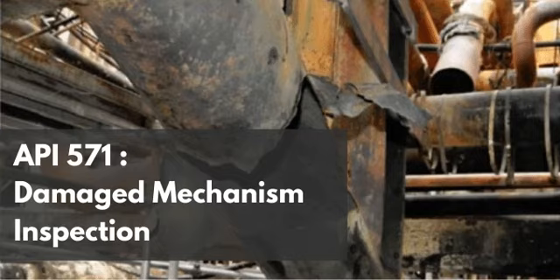There is a massive environmental wildcard that hypercharges this reaction, right? Yes, oxygen. The documentation is incredibly clear that contamination with even microscopic trace amounts of air or oxygen dramatically increases the tendency toward cracking. Oxygen is the catalyst that turns a latent vulnerability into a catastrophic failure, especially in anhydrous ammonia environments.